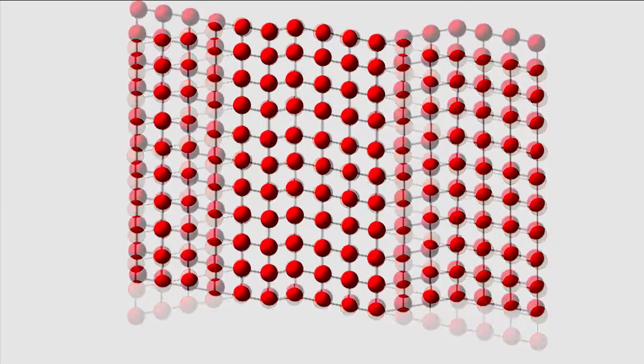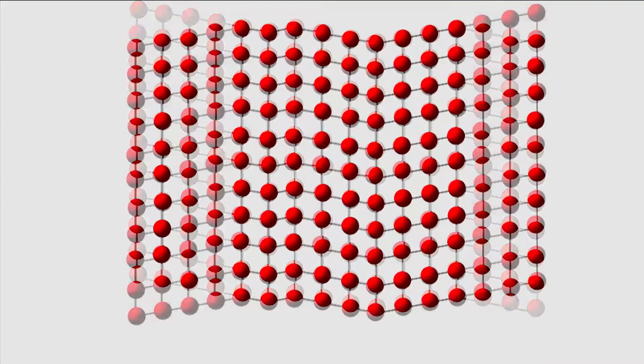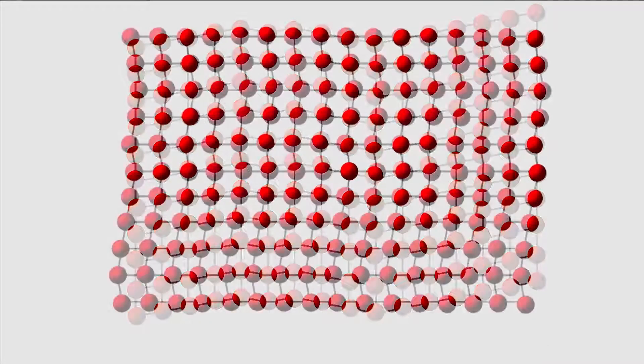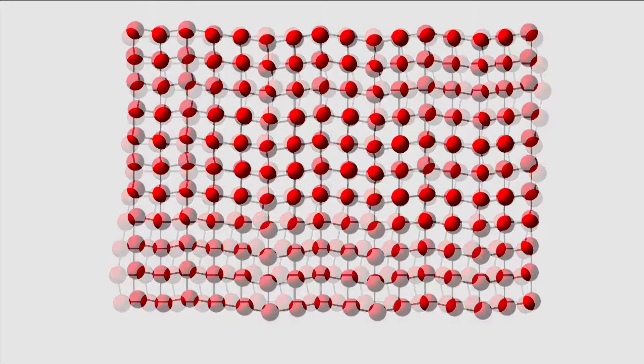But notice this. At all times, the atoms are connected in the same way as in the high temperature phase, unlike in slip, where atoms can rearrange quite a bit more.